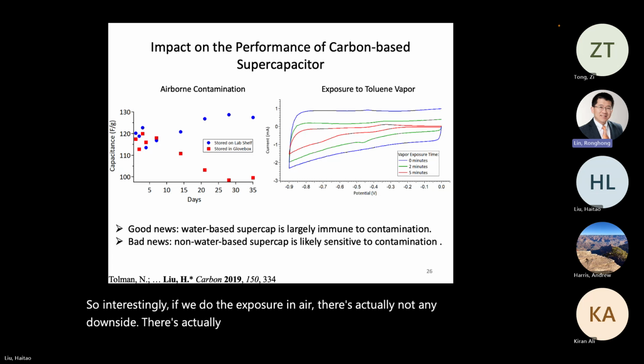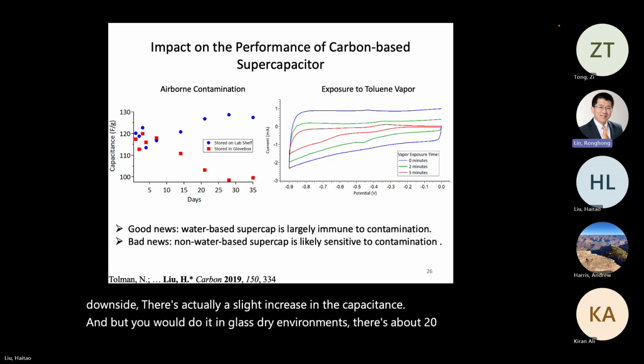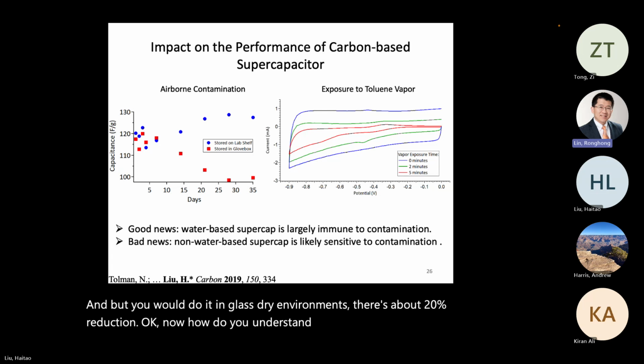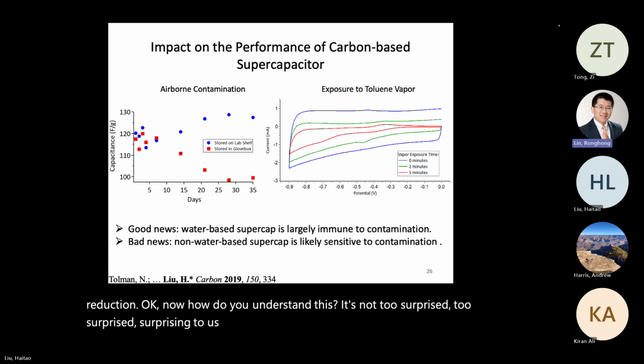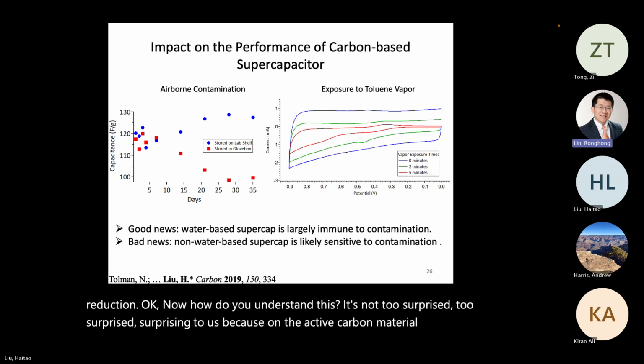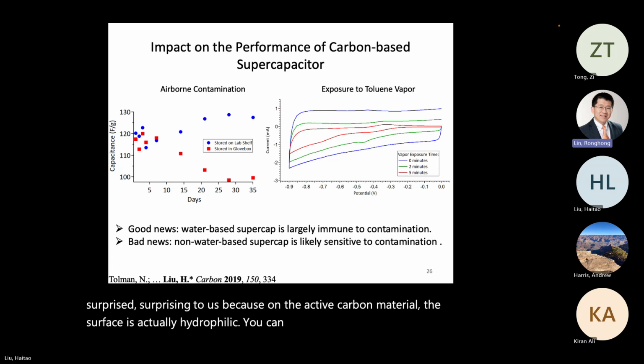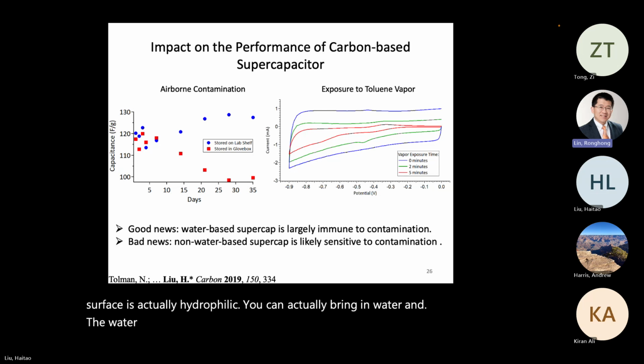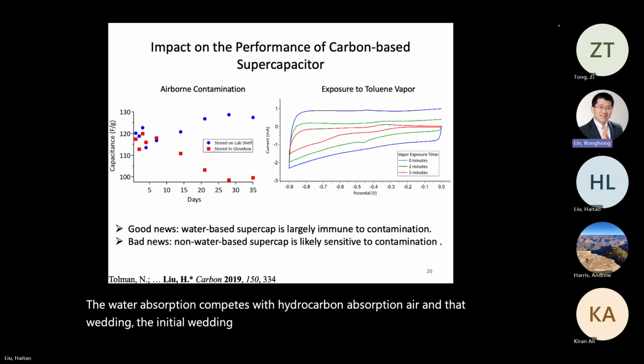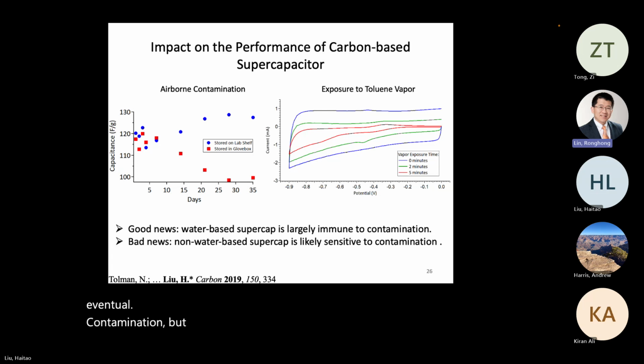There's actually a slight increase in the capacitance. But if we do it in glove box, dry environments, there's about 20% reduction. Now, how do you understand this? It's not too surprising to us, because on the active carbon material, the surface is actually hydrophilic. You can actually bring in water, and the water absorption competes with hydrocarbon absorption in air. And that wetting, the initial wetting, fills the pore and prevents the eventual contamination. But that mechanism does not happen in a dry environment.